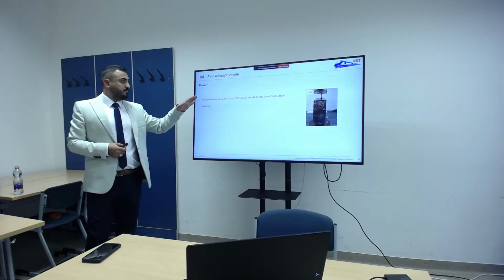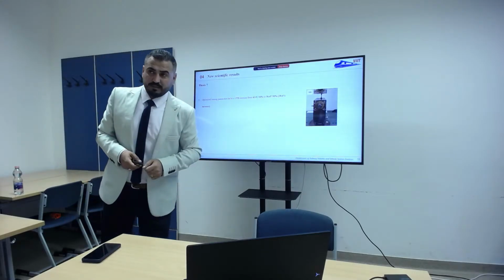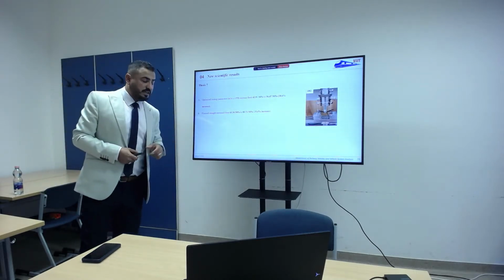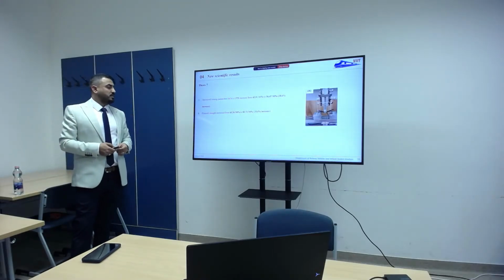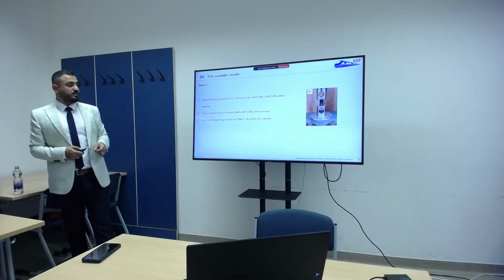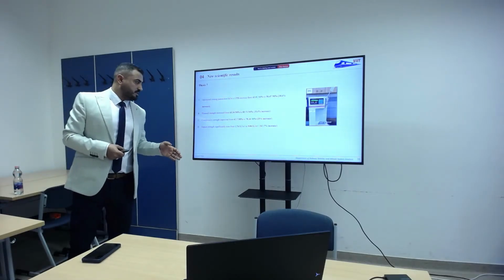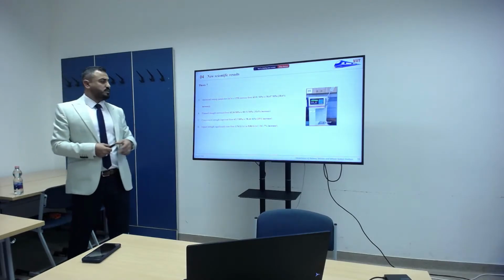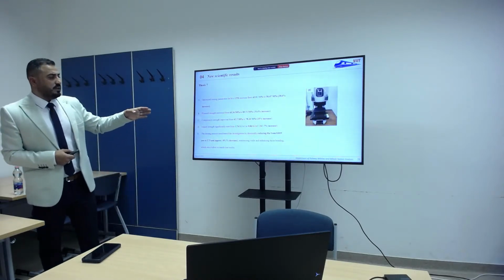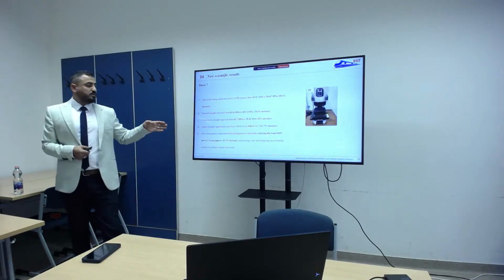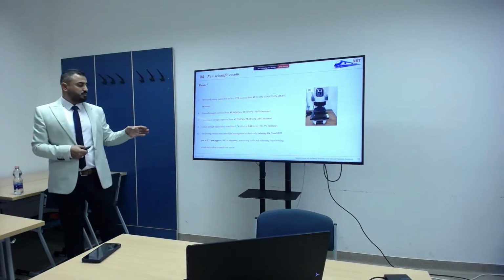So for the ultimate tensile strength, I increased the value from 43 megapascal to 56 megapascal, about 28% increase. For the flexural strength, it increased about 35%, from 63 to 85 megapascal. For the compressive strength, I improved it from 62 to 78 megapascal, about 25%. For the impact strength, it rose significantly from 3.7 kilojoule per square meter to 9.84 kilojoule per square meter, about 161% increase. And the surface roughness decreased by about 70%, from 8.8 micrometers to 2.73 micrometers.